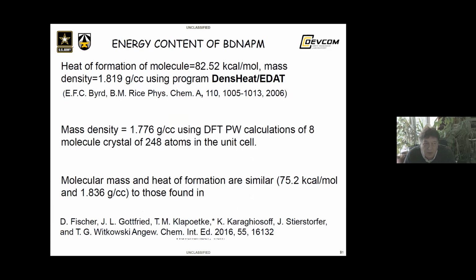The best and most reliable method to calculate heat of formation of energetic molecules is the EDAT heat method developed by Ed Byrd and Betsy Rice in our lab. It is based on a reasonably accurate calculation by Gaussian of the molecule and some fitting combined in a set of scripts. The mass density calculated in EDAT and crystal DFT and the estimate of heat of formation are comparable with those found in Klapötke's paper. These are theoretical calculations.